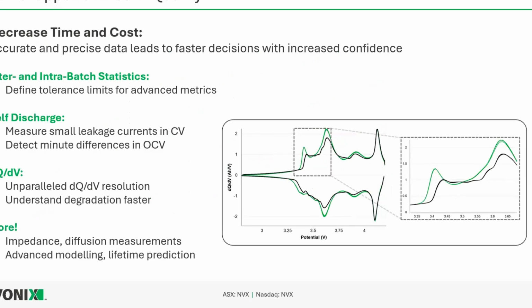So where are the opportunities for QC? Really, this comes at decreased time and cost. Where can we use UHPC to fill those gaps? So inter- and intra-batch statistics, so defining tolerance limits for some of these advanced metrics. If you were able to take just a small subset of cells, every lot of cells that's made, or every time a material is changed, and use some of these very fine insights in a very small amount of time, you may be able to determine that there's some kind of change between lots as we're moving on, as the normal QC process is happening.